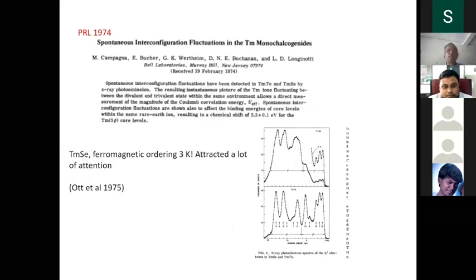Subsequently, even thulium selenide was also found to exhibit this. What I want to say is that this phenomenon became widespread. It started with cerium, went to samarium, and now you find even thulium. In other words, wherever two valence states are possible, there's a tendency for the electron to go out of the orbital and come back. Therefore, the so-called valency, as originally believed, can actually fluctuate, and you can have an intermediate valence state as a function of temperature or pressure. In this case, at ambient pressure, even thulium selenide was found to show it.